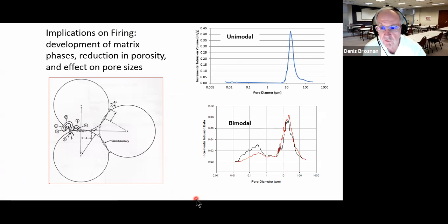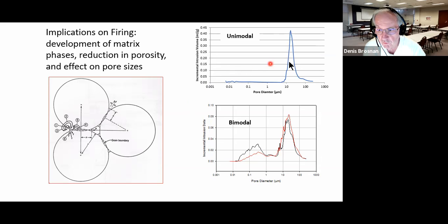Just to reinforce what I just said, a unimodal pore size distribution is one like shown right here. In other words, most of the pores are right around a particular size, and this is showing it just above about 10 microns or thereabouts. But if we fire to a lesser extent, this may be maturity and this may be a little bit immature, then not only do we have those pore sizes up here above about 10 microns, but we start developing pores down here below 1 micron, between 1 micron and 1/10 of a micron. And those are the fine pore sizes that provide the spalling resistance. So you have to define maturity in terms of what characteristics you want in the product. And pore size distribution then becomes just as important as porosity and strength.